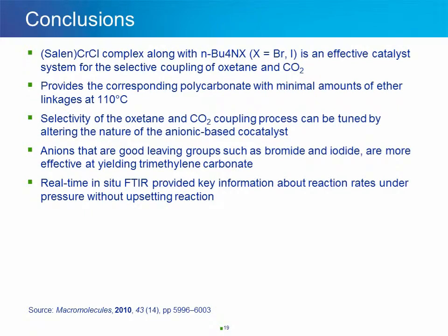Furthermore, at lower reaction temperatures, temperatures less than 80 degrees C, the catalyst system is capable of producing polycarbonate directly from ring opening polymerization of preformed TMC via a coordination insertion pathway.